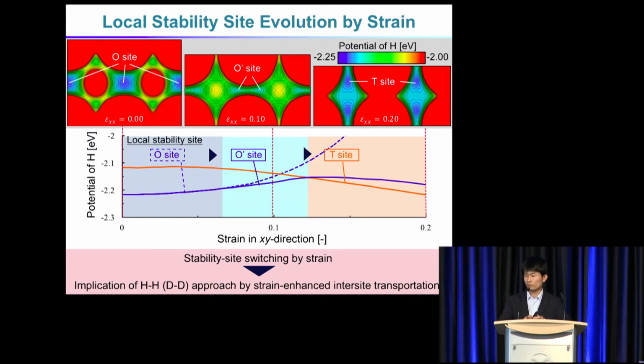And this is the result. In summary, we observed in our simulation a shift of the stable site. As you know, in the standard condition, the octahedral site is the stable one. However, it shifts into the tetrahedral T site due to the strain.